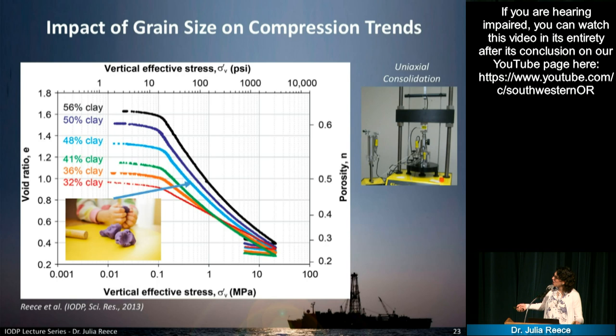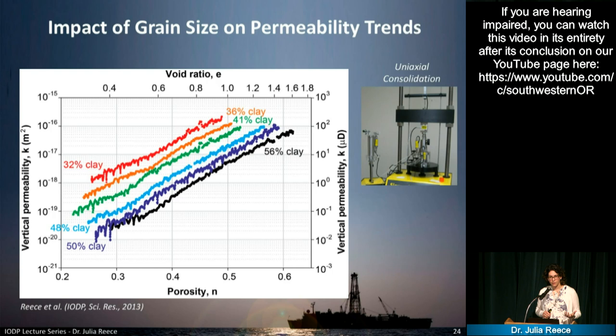And then you see in the middle the slope, the angle of this line, is changing, and also the porosity here is systematically dropping as we add more and more silt to the mixture. And so we compress this all to 21 megapascal, which is about 2 kilometers below the seafloor. And then we can also infer permeabilities from these tests.